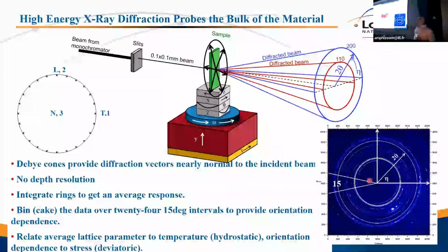Where we're lucky is that the majority elemental materials in stainless steel, iron, nickel, and chrome, all have very close to the same metallic radius. So we will see that the chemistry does change in this, but it doesn't affect the lattice parameter very much. So this is one of those pieces of external knowledge that allows me to exclude chemistry evolution when I try to separate temperature from stress. And I'll separate that temperature and stress first by finding the radius of the rings, which is what's related to temperature, and then the ellipticity of the rings, which is what's related to stress.